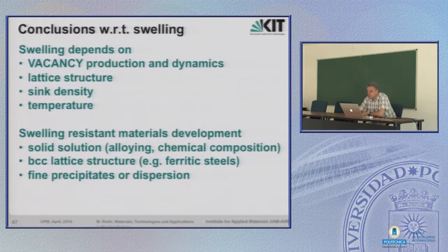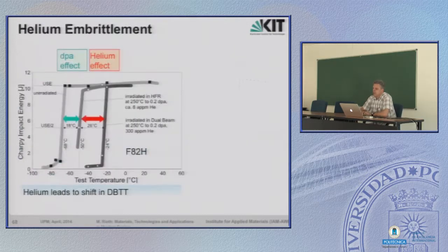Now we are almost through. The only remaining question is what happens with helium and the helium bubbles and helium transmutation. How does helium affect the material properties? Here was a very distinct study where a 9% chromium steel has been tested by Charpy test. Then we have produced only this displacement damage, this hardening, which shifted the DBTT by around 20 degrees C.